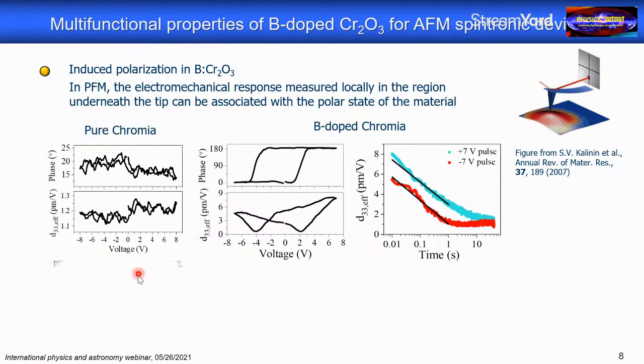that it's not ferroelectric. The polarization that you create by applying an electric field relaxes when you remove the electric field. So there's no spontaneous polarization, it is just induced. Here you see the relaxation happening on a rather significant time scale, on the time scale of a second. So it's a slow relaxation process here. And the control experiment tells us that in pure chromia, this phenomenon is absent. So there's a real qualitative change. If you compare with pure chromia, you see the data here, neither in the phase nor in the piezo coefficient do you see any significant features.